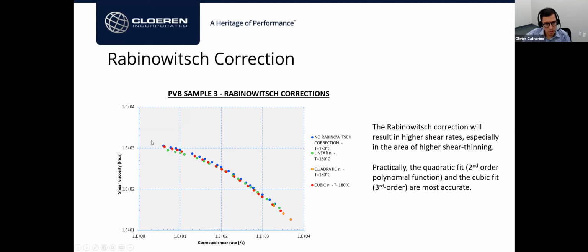But what I like though is that at low shear, where the material becomes more Newtonian, locally the pseudoplastic index should be getting close to 1, and your Rabinowitsch correction should be almost none. And so these two corrections make sense because the blue measurements, uncorrected and corrected, sort of make sense here. At the low shear rates, the linear was correcting too much, I think. Because of that, what I just meant is that when you're close to the Newtonian plateau, you should not have any correction. In the Newtonian plateau, you should have a zero correction. And this is what you are seeing with the quadratic and cubic.